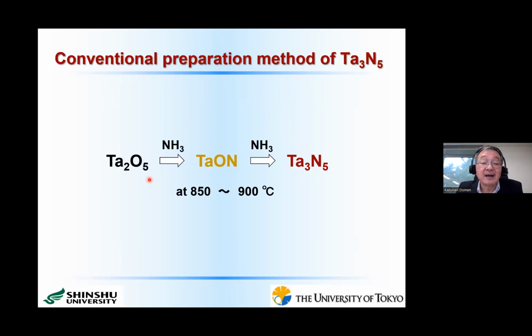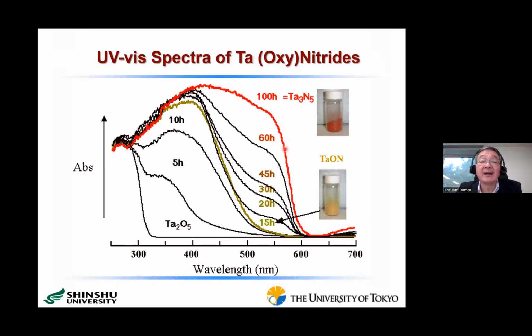In this case, we use tantalum pentoxide as the starting material, then nitride it by atmospheric pressure of ammonia at 850 to 900 degrees C. At first, tantalum oxynitride, TaON, is formed, and then Ta3N5 is formed. To see this change in detail by UV diffuse reflection spectra, I show the change of the diffuse reflection spectra of these materials. In this case, we intentionally slowed down the nitridation rate to see the change clearly.